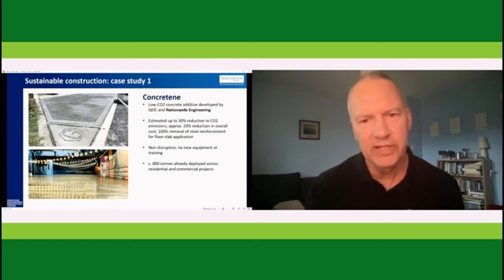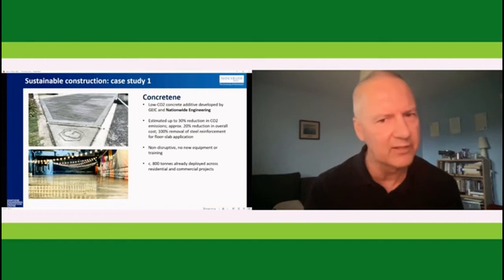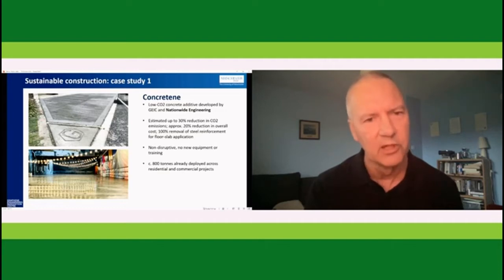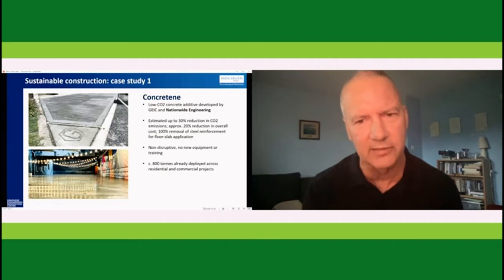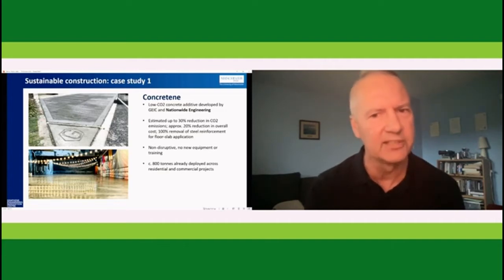So what we're really doing is this living lab. Through doing these real pours, we found out additional information. For example, as well as the improved performance using less material, we've also found that we achieved the cure cycle or the cure time within 12 to 24 hours that typically can take up to 28 days. So again, that's quite transformational.